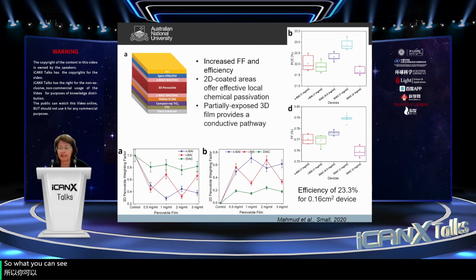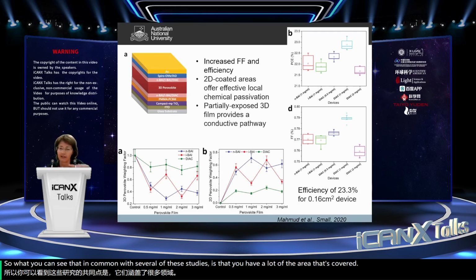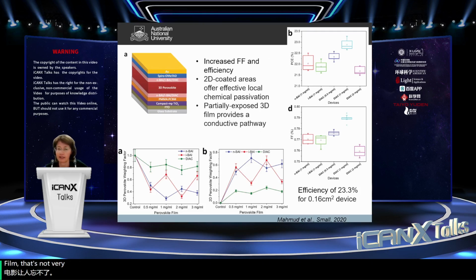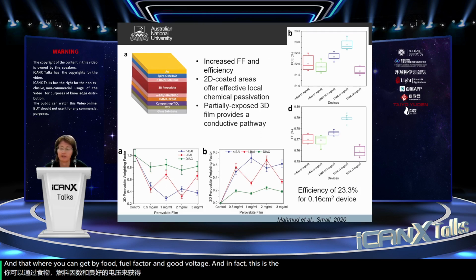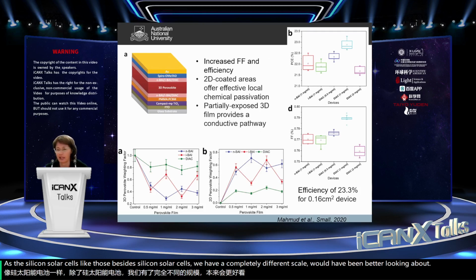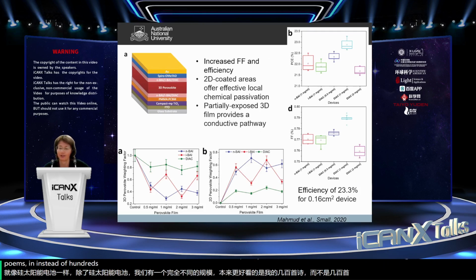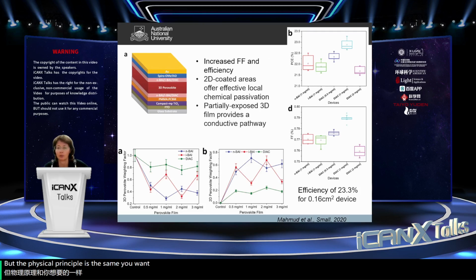So what you can see that's in common with several of these studies is that you have a lot of the area that's covered with film that's not very conducting, and that improves the voltage. But there are regions that are exposed and give you better conduction, and that way you can get both good fill factor and good voltage. In fact, this is the same physical principle as the PERC silicon solar cells. In those silicon solar cells, you have a completely different scale, where they're talking about hundreds of microns instead of hundreds of nanometers. But the physical principle is the same. You want to have most of the area passivated and only some areas exposed, allowing that conduction.